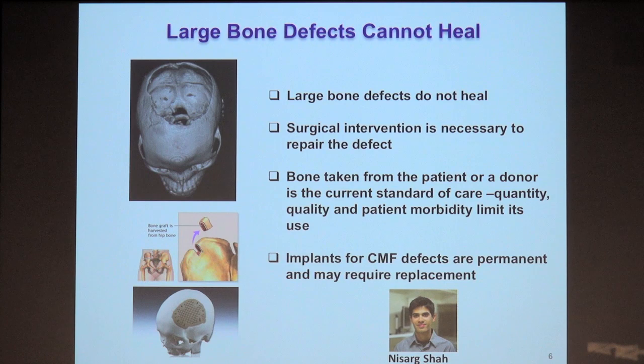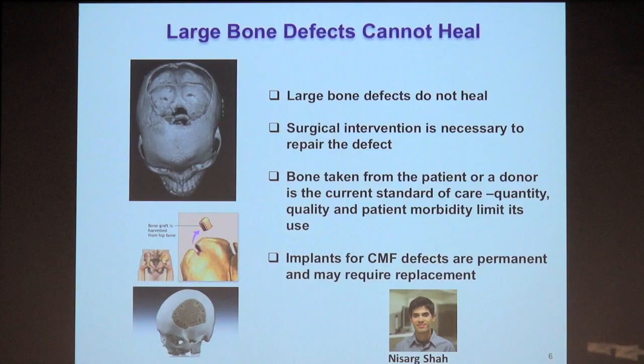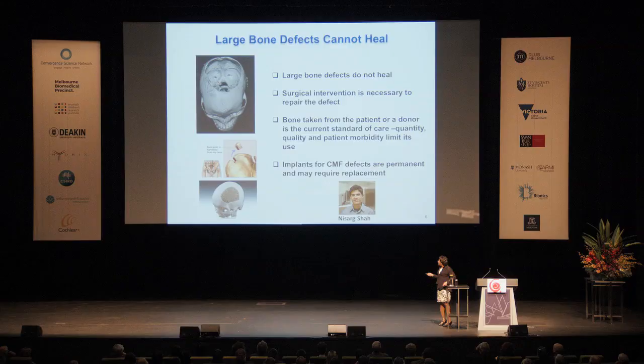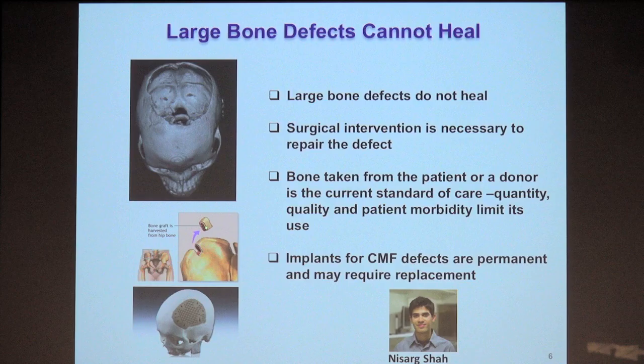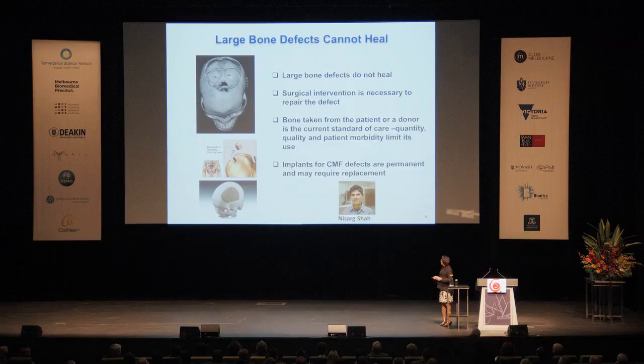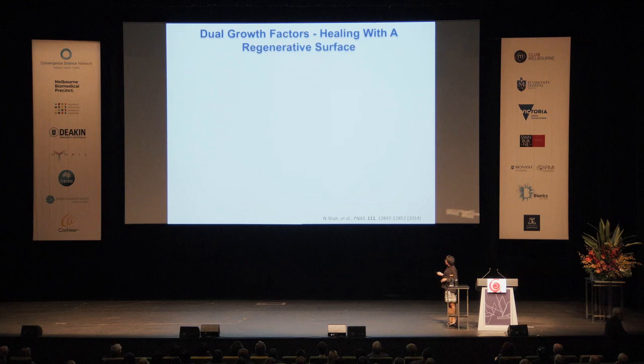Now, what Nisarg did was use a combination of my favorite polymer, polyester, in combination with a layer-by-layer assembly to replace state-of-the-art. State-of-the-art is that you take a graft from the bone, and so this poor patient has to lose some more bone, and grind it up, create a paste, and maybe you apply that to some sort of metal or plastic implant to try and regenerate the growth of bone. Or you use stem cells. We're interested in a cell-free approach in which we can essentially generate a membrane that's very easy to make.